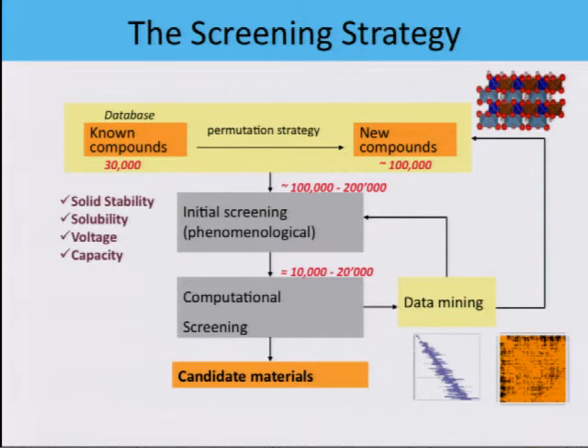But we can permute them. So we can take the crystal structures and look at the different cations in them, and substitute other elements and that way generate new materials, new starting points, new candidates. We looked at about 100 to 200,000 materials. We calculated first a few of them, and by few I mean a few thousand. We data mined that result for the things we wanted: voltage, capacity, stability. And then we fed that back into the loop. We generated new compounds that would be better guesses and better fits. We screened those. And in the end, I think we computed about 10,000 to 20,000 by first principles.